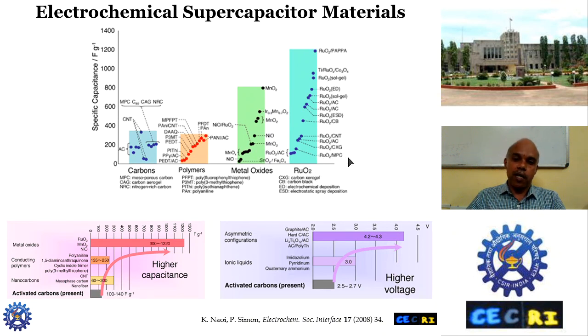These two are known as pseudocapacitors, but the cost of ruthenium oxide is high. So to minimize the cost, we can explore making composites or improving the properties of manganese oxides. For example, here it is shown that from activated carbons to different types of metal oxides like ruthenium oxides and manganese oxides, the capacitance has increased up to 1200 farad per gram. Similarly, the voltage can be improved. If you are using an aqueous electrolyte, the voltage is limited to 1.2 volt or even less. But if you go with organic electrolytes, your voltage can be increased. Or you can also use ionic liquids, or make asymmetric configurations of the capacitor materials, so that you can increase the operating voltage of the capacitors.